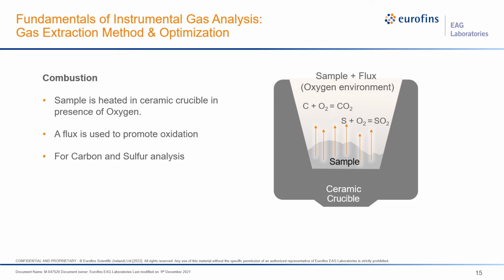The next gas extraction method is combustion. In this method, the goal is to combust the sample in an oxygen environment. The sample is heated in a ceramic crucible in the presence of oxygen. Different types of flux material are used that can promote oxidation and lower the melting point of the sample. This method is used to analyze carbon and sulfur, which are detected in the form of CO2 and SO2.